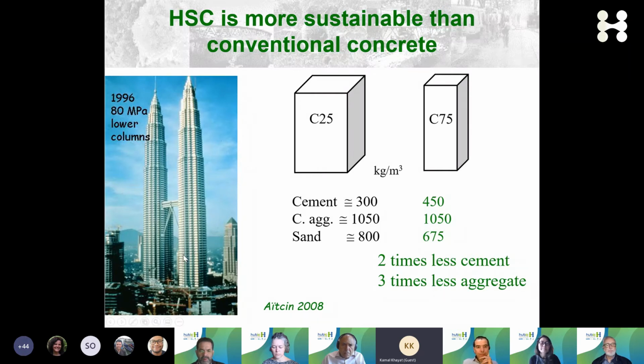This is a typical high-rise building, the Petronas Towers. And you can see if you were to use a compressive strength of 75 MPa, you can reduce the element size versus 25 MPa. And although you are using more cement and more materials, comparing element by element in the building, you can be saving 2 times cement and 3 times aggregates, both coarse and sand, if you are using high-strength concrete. So that's also a mega trend, using high-strength concrete to reduce section widths.